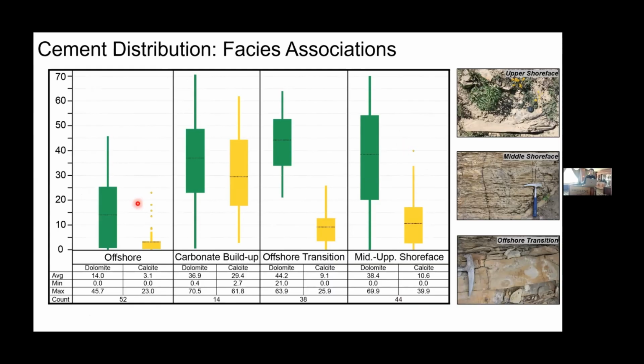So starting off with the offshore deposits, we see relatively low amounts of both dolomite and calcite. Moving to the carbonate buildup, we see a pretty wide range of both dolomite and calcite cements. However, these facies have the highest average of calcite content, I should say, and that's due to the fact there's a lot of detrital allochems present in that interval that can explain why the calcite is so much higher relative to the others. So they're not diagenetic.